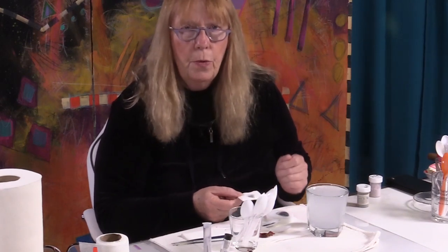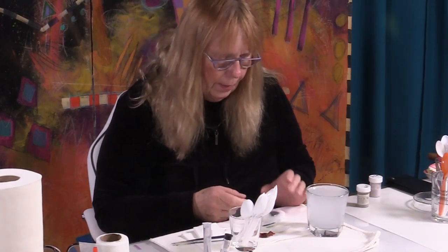I rarely set my piece on top of the kiln to dry, because if it gets too dry, then when you pick it up to move it into the kiln, the very dry enamel just cascades off of the edges of the dome slope. You'll actually work against yourself if you make them absolutely perfectly dry before you put them into the kiln. I like a little bit of moisture — not so much that it's going to boil, but enough so that I can lift it up and get it into the kiln without that cascading dry powder off the edge.